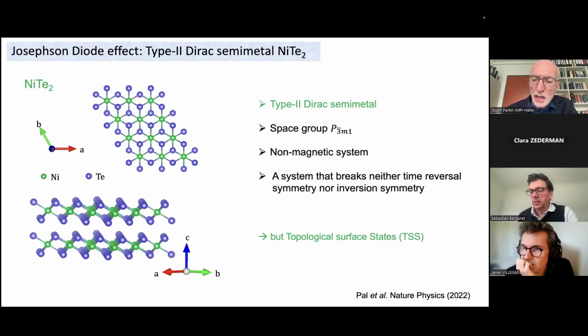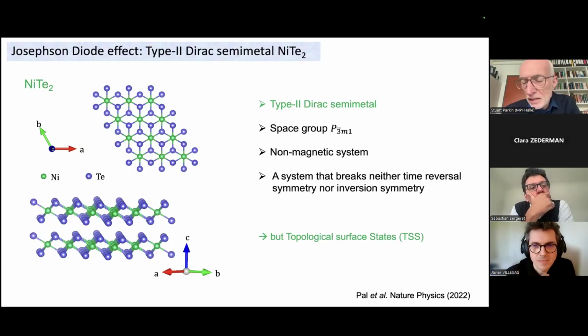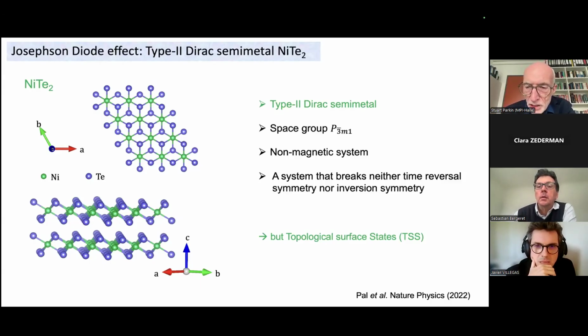However, what's interesting in the system, and the reason why we chose it is, although it's non-magnetic and not superconducting, nevertheless, this system has so-called topological surface states. It's a so-called type 2 Dirac semi-metal. So on the surface, you'll find states which are actually spin polarized when you pass a current into the system. The current will flow and the spin of the electrons are coupled to the direction in which the electrons flow, so that the spin of that electron will be orthogonal to its direction. So this can lead to spin polarized surface states. This is the reason why we chose this system. Otherwise, this system is centrosymmetric and non-magnetic. It breaks neither time reversal symmetry nor inversion symmetry.